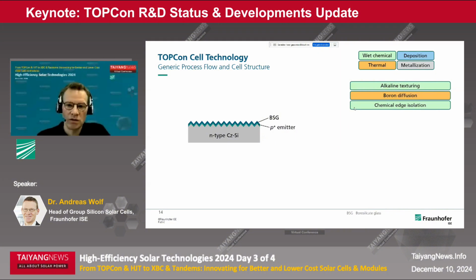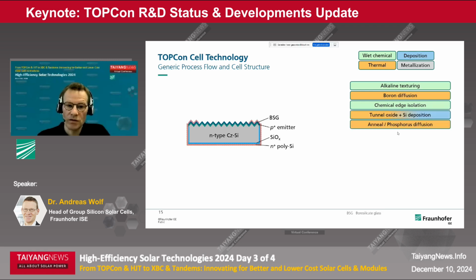I will share some details on this soon. And this process also planarizes the rear side. Then the TOPCon system is formed by tunnel oxide growth and silicon layer deposition, as discussed previously, might be doped or undoped, and in a subsequent step, the annealing is performed or the phosphorus is provided to the undoped layer.